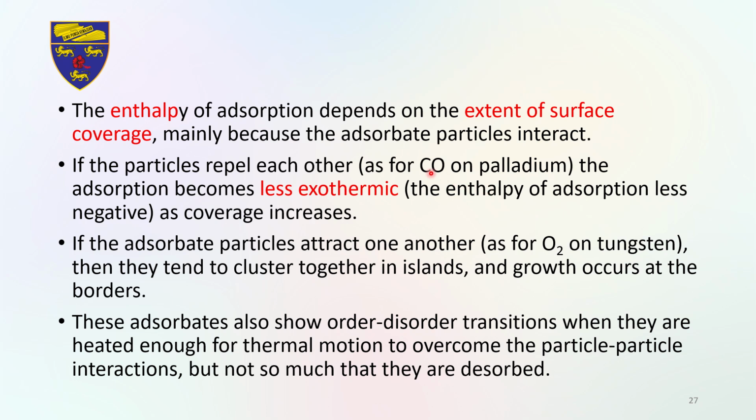The enthalpy of adsorption depends on the extent of surface coverage, because the adsorbate particles interact with each other. If the particles repel each other, for example carbon monoxide on the surface of palladium, then the adsorption becomes less exothermic as the coverage increases.